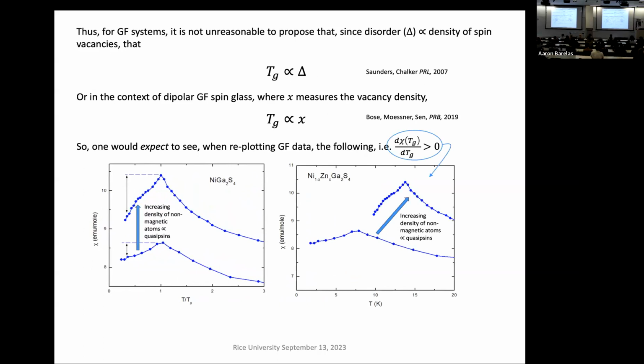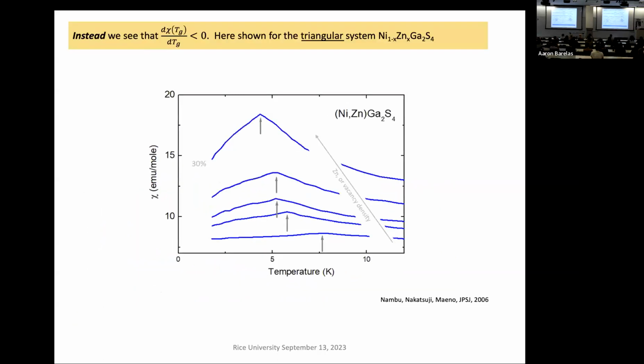Instead, what we see, and this can be expressed as d chi at Tg over dTg greater than 0, that's not what happens. Instead, this is what happens. So the collective energy goes down, and the signal goes up. Okay? I've known about this sort of data for a long time. I'll show you the original data.